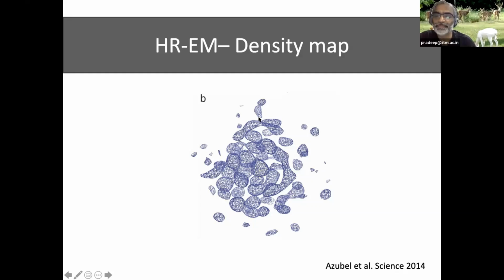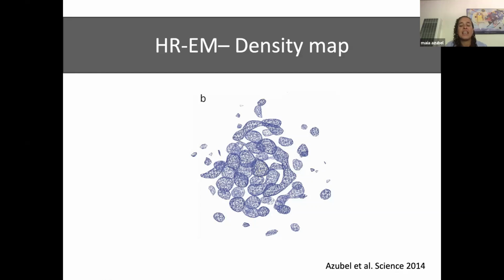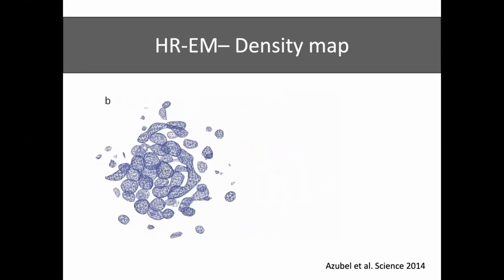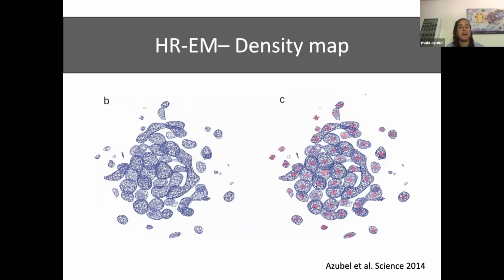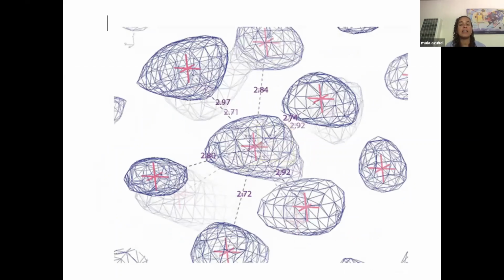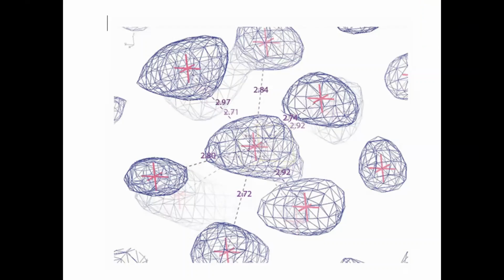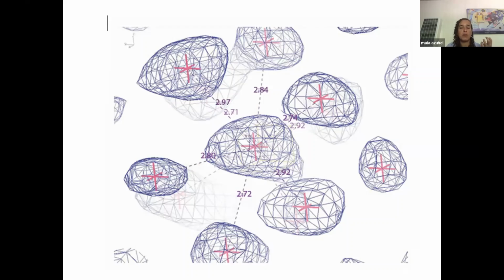Okay, so one of the things that I did with this cluster is do a peak search. And that got more interesting. When I did a peak search, I found 68 peaks. Even more interesting than that was the fact that the distance between peaks was between 2.7 and 3 angstrom. And we already knew from the gold 102 that was solved by X-ray crystallography and other clusters that came after that that was the distance that was expected. So yes, each of these peaks that I was seeing were the peaks that correspond to gold atoms.